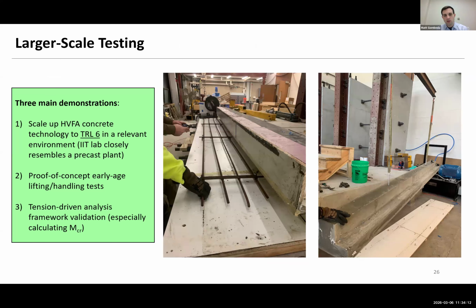So we did some larger scale tests with some inverted T-beams, and our lab is kind of like a mini precast plant. So we were able to actually fabricate everything in-house and test it in the same space. Kind of a unique thing that we can do here. But if you look closely, you can see there's a maturity sensor on the far end. So it's monitoring, like I said, the temperature in the concrete. And then one of those sensors is also put in a cylinder when you do the test for the compressive strength. And then you can correlate the temperature for both specimens, and we have information that helps us predict what the strength in this beam is before we even test it.